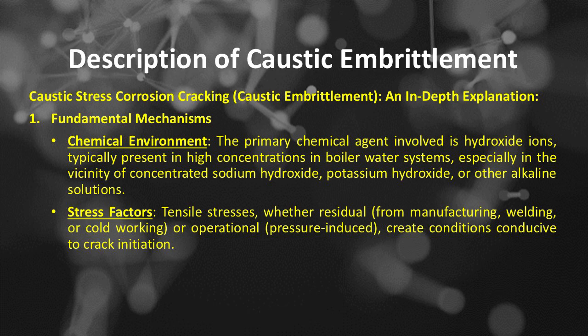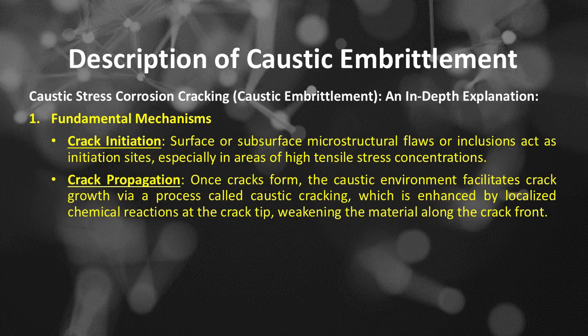Number 1 is fundamental mechanisms of caustic embrittlement. Chemical environment. The primary chemical agent involved is hydroxide ions, typically present in high concentrations in boiler water systems, especially in the vicinity of concentrated sodium hydroxide, potassium hydroxide, or other alkaline solutions. Stress factors. Tensile stresses, whether residual, from manufacturing, welding, or cold working, or operational, pressure-induced, create conditions conducive to crack initiation.